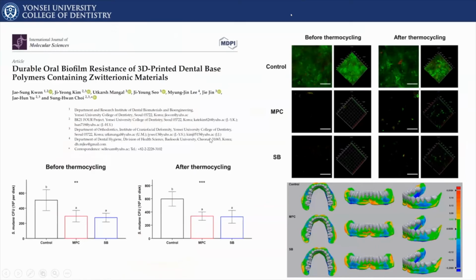So we wanted to incorporate it into a number of different materials. We then published a lot of papers to see whether this has the potential to be incorporated in different materials, such as 3D printing materials like here. The incorporation of zwitterionic materials was pretty much possible on many different materials, and this was much more durable in many senses. When we consider before and after the aging process with thermocycling, the effects were pretty much maintained because they are locked into this polymer matrix and provide the effects as a bulk form.